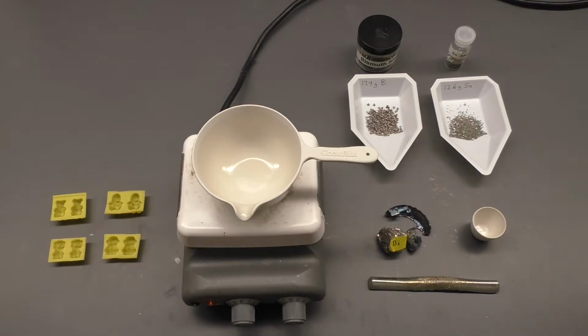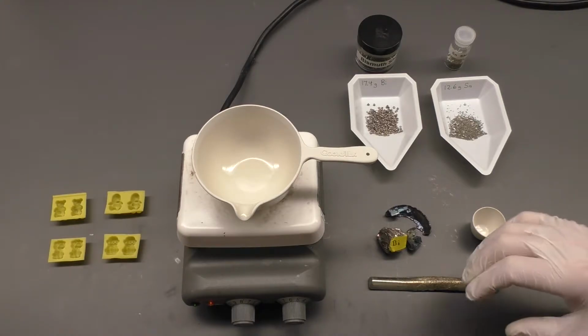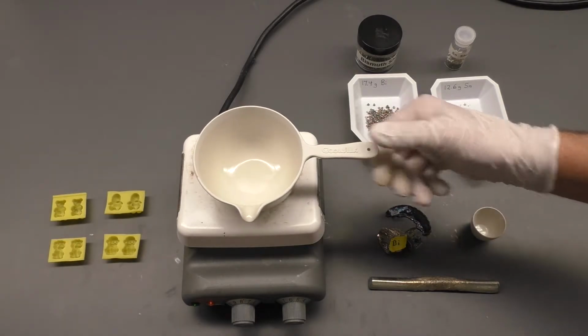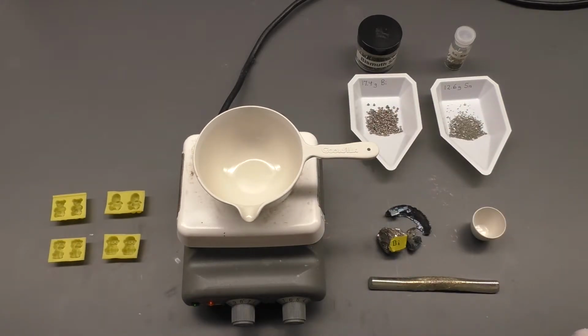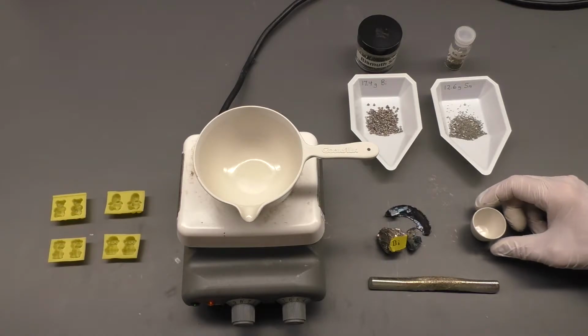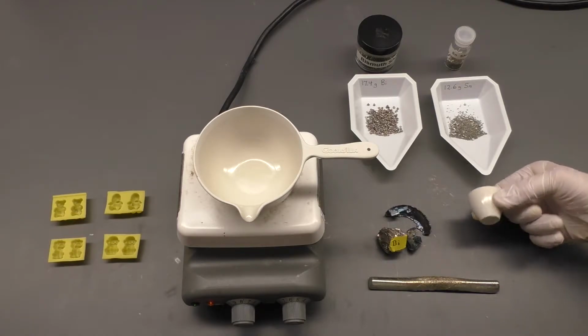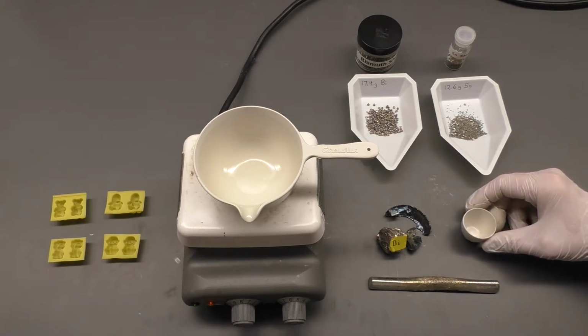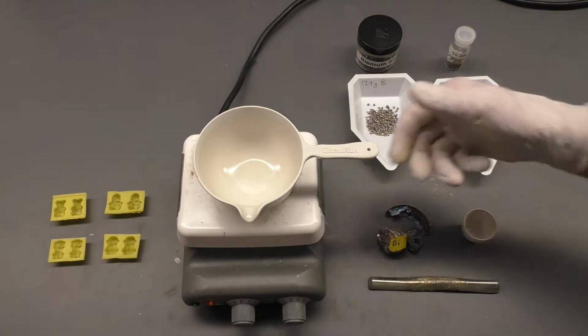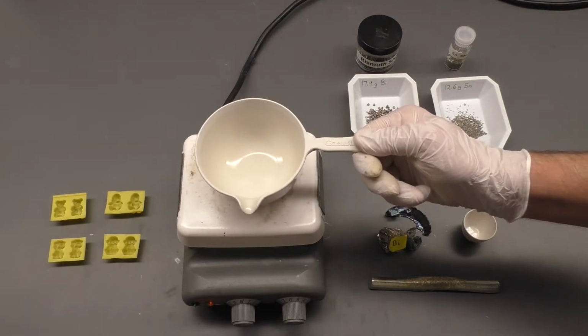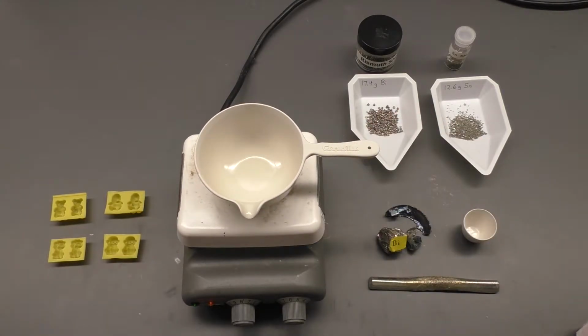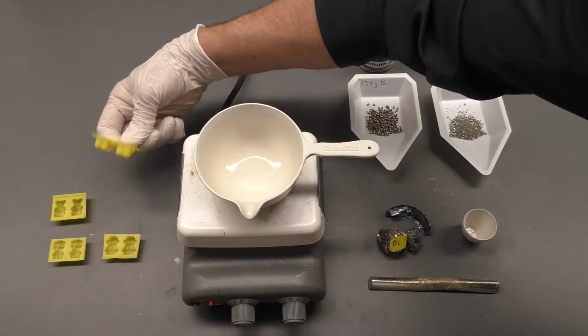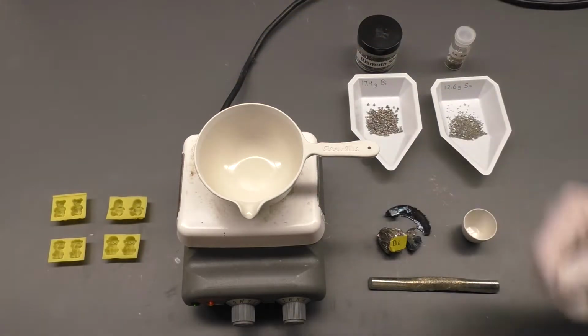We're going to take those two and melt them together in this gigantic crucible. Now normally when you do this in lab, you would be using about 1/3 of the amount that we're going to use, and you would use a tiny little crucible, just a ceramic little cup that is very heat resistant. But we're going to do a little bit more. We have this much larger crucible that we're going to melt the materials together in. Then once they're molten, we're going to go over here and pour them into little molds and make little trinkets.